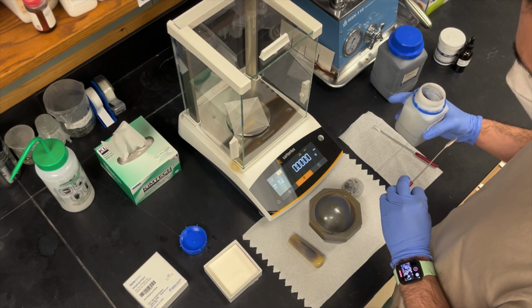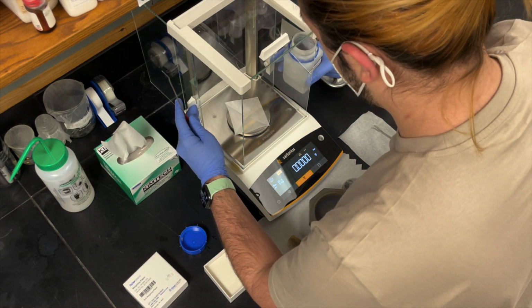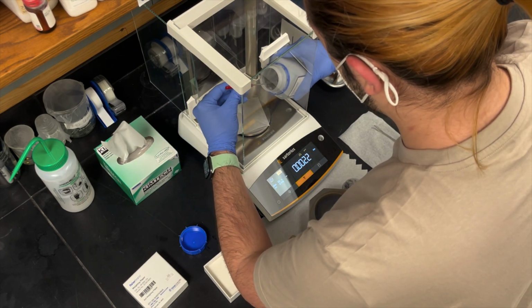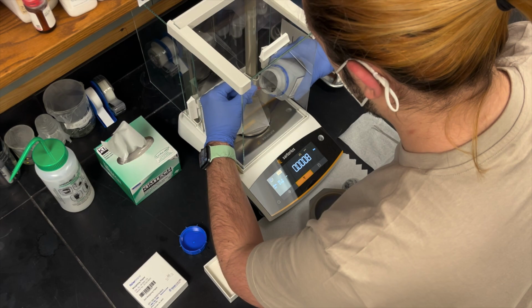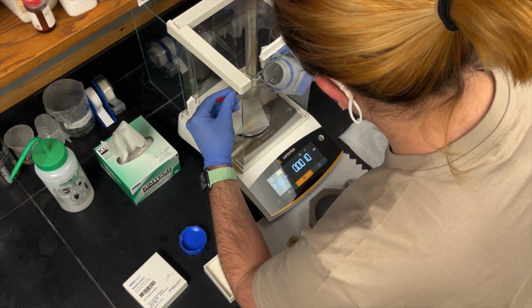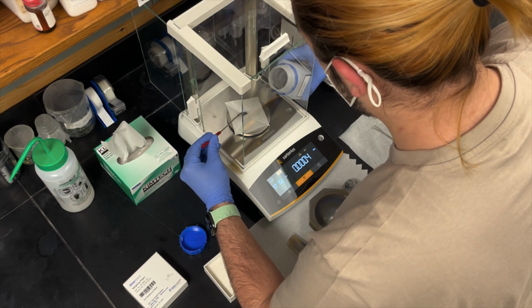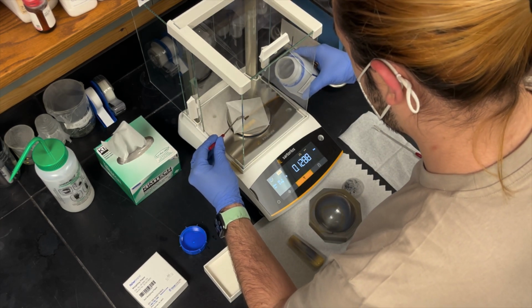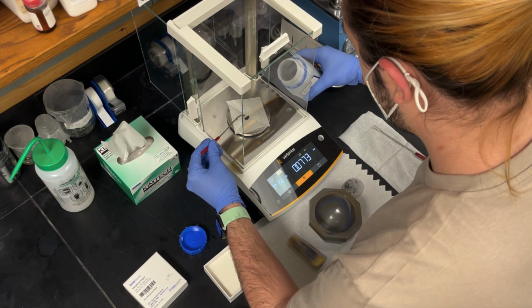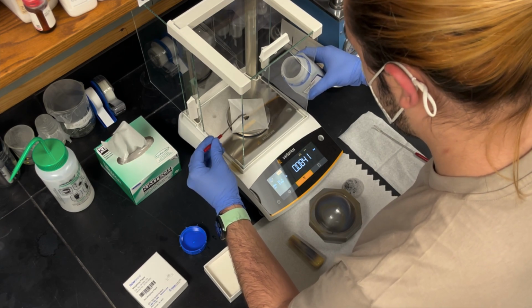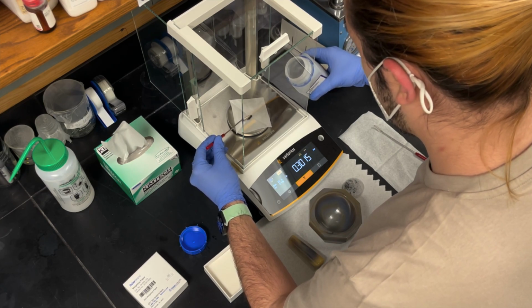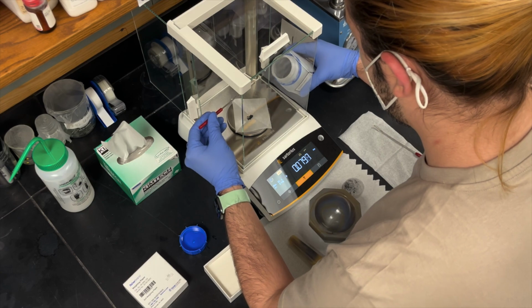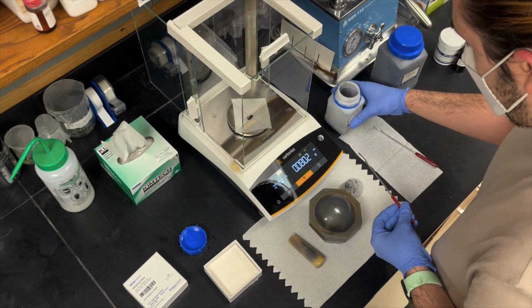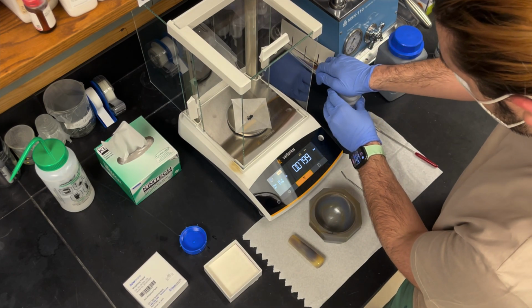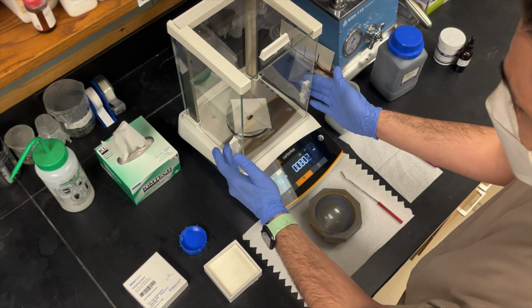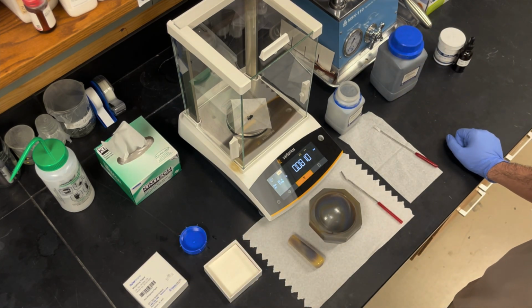To start out, I'll be weighing 80 milligrams of the active material, the nickel, cobalt, manganese powder, to create the cathode slurry. It's typically easier to start adding in a little bit at a time because it'll be easier then to put just a little bit more on rather than having to take more off. Having finished weighing the material, I'll be shutting the balance and allowing the air currents to come to a stop so that we can take the measurement.